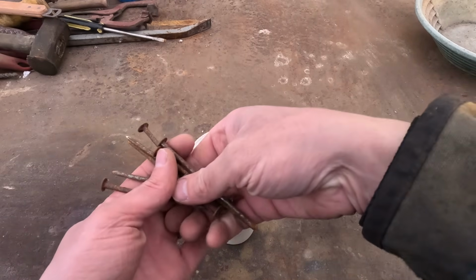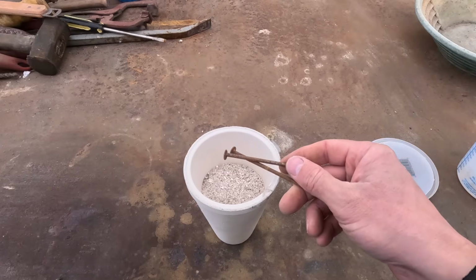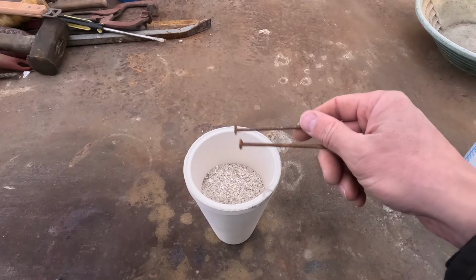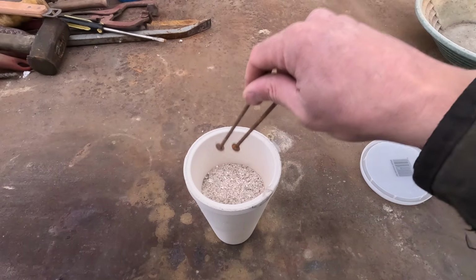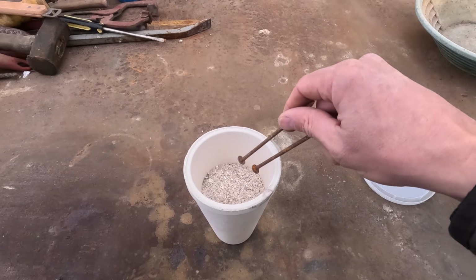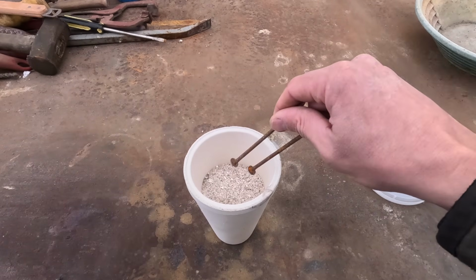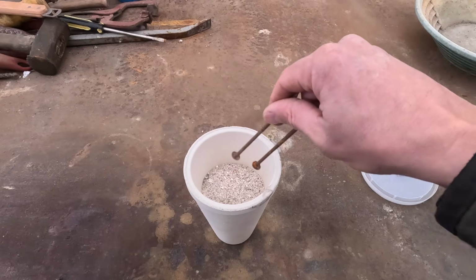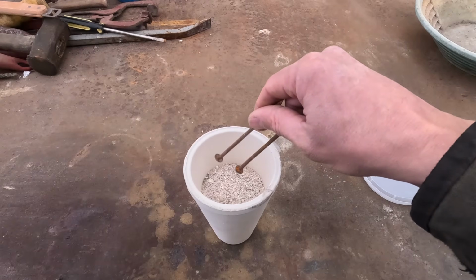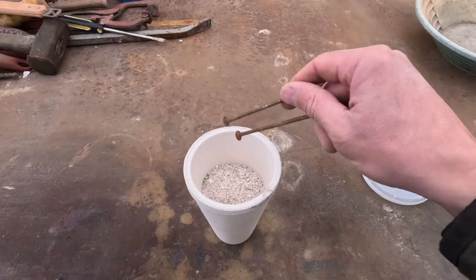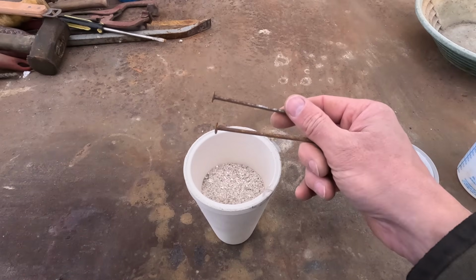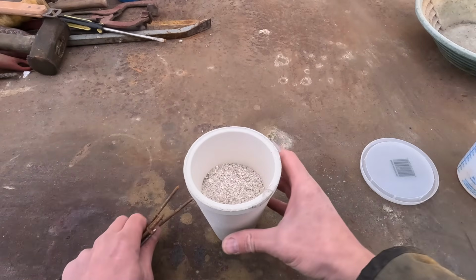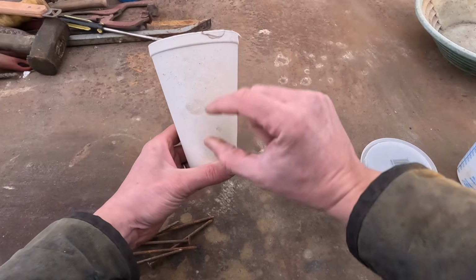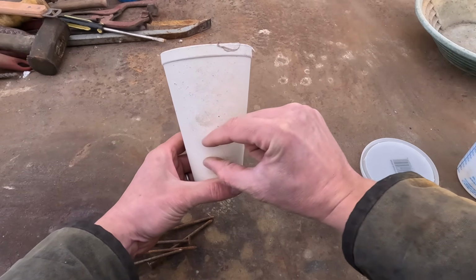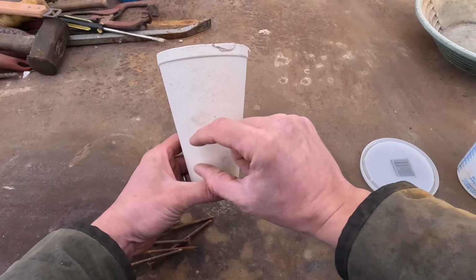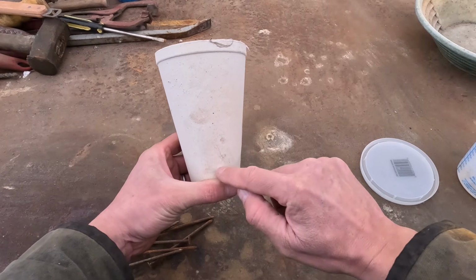All that chemistry we talked about earlier is based on the iron nails being in there, and it is able to react with that. Because I've put oxidizers in there, potassium nitrate and bismuth oxide, I'm gonna let that chemistry happen first. So I'm gonna let this slag form, everything in there that's gonna oxidize, I'm gonna let it oxidize. And then once it's all fluid, I'm gonna put the iron nails in at the end, where we should have a slag. There will probably be a matte layer in here before I add the iron nails, because I don't have enough oxidizer to oxidize everything. And then a metal button at the bottom.